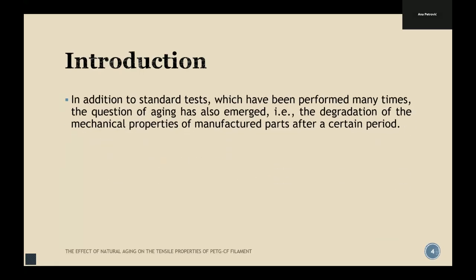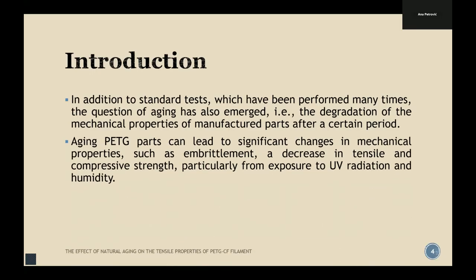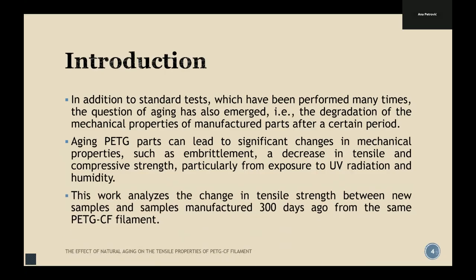In addition to standard tests, which have been performed many times, the question of aging has also emerged: the degradation of mechanical properties of manufactured parts after a certain period. Aging PETG parts can lead to significant changes in mechanical properties, such as embrittlement and decrease in tensile and compressive strength, particularly from exposure to UV radiation and moisture. And because of that, we want to start our project.